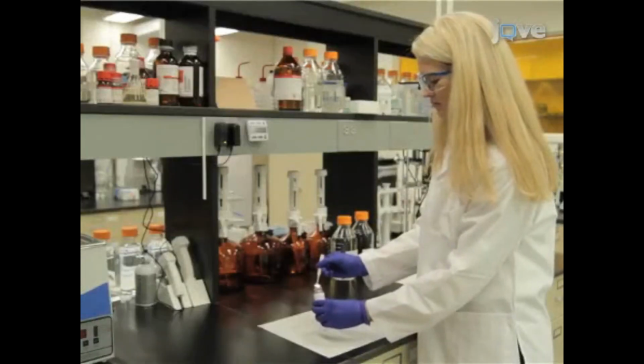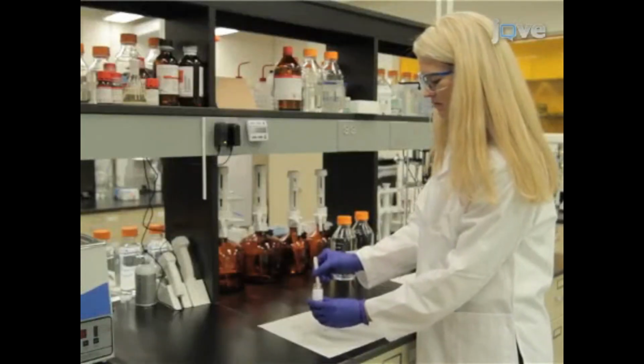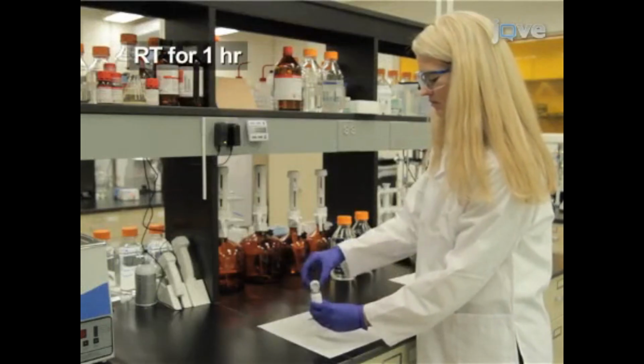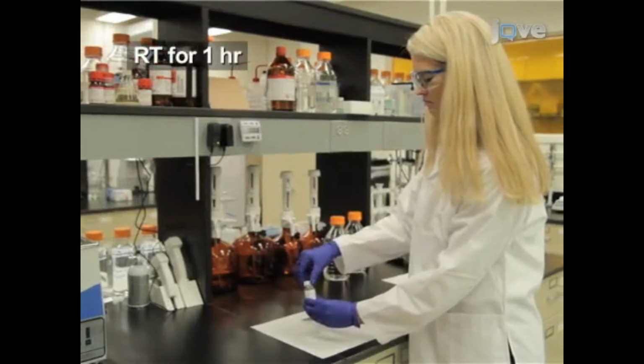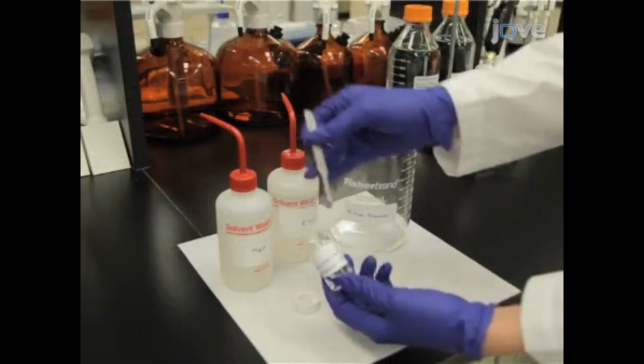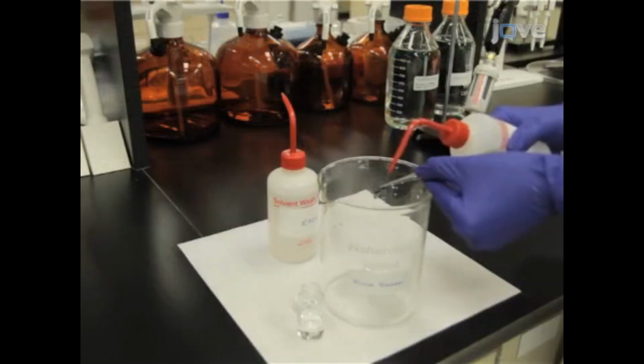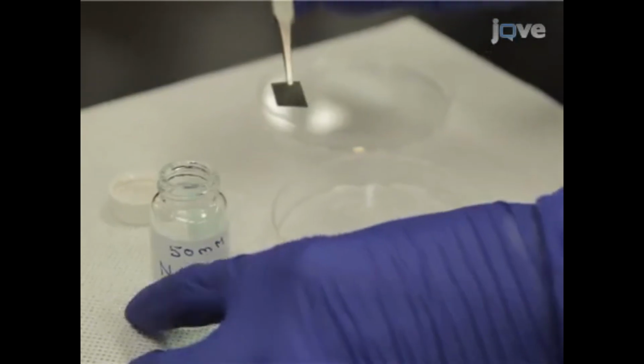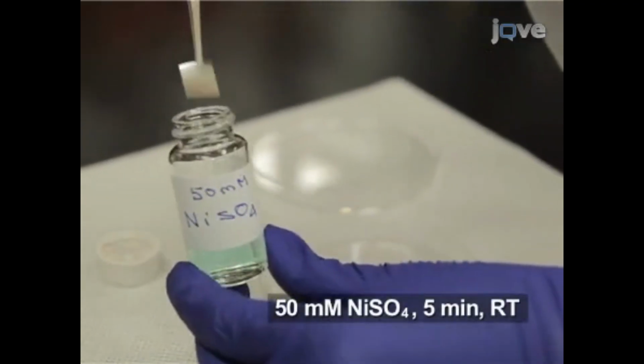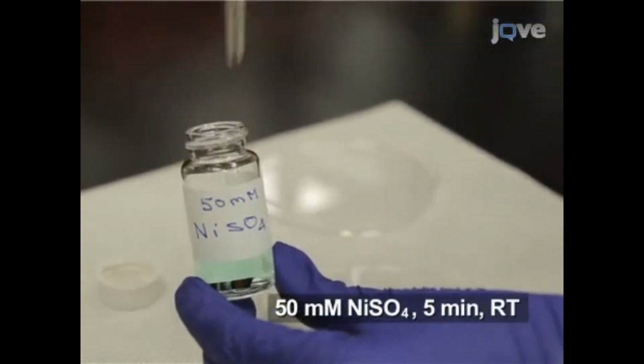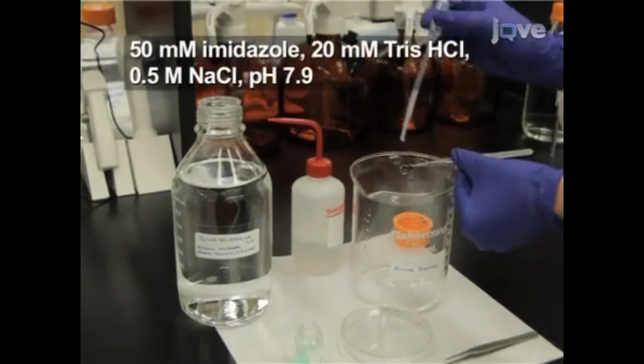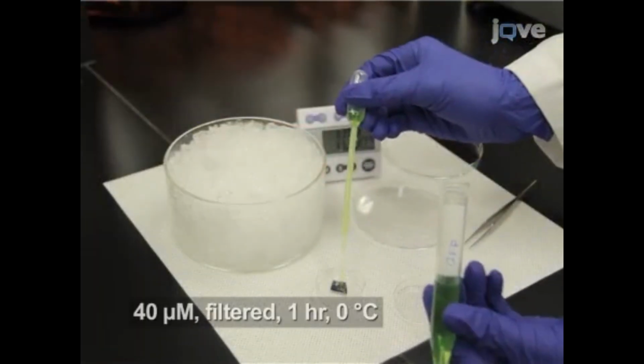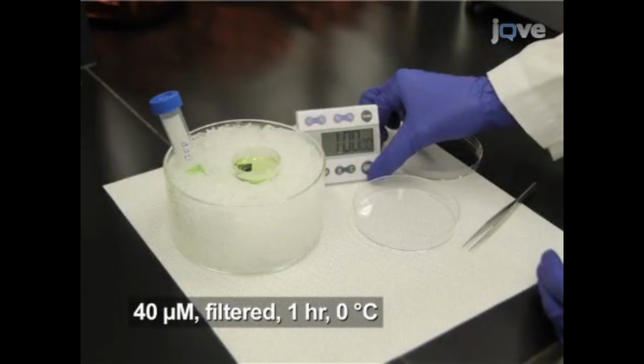To attach proteins to the NHS patterned bifunctional substrate, submerge it in a solution of lysine NN-diacetic acid and triethylamine. After an hour, rinse the substrates with water, followed by ethanol. Now, incubate the substrates for 5 minutes in a chelating solution of nickel sulfate. Next, rinse the substrates with water and binding buffer, followed by submerging them in a bath of ice-cold GFP solution.